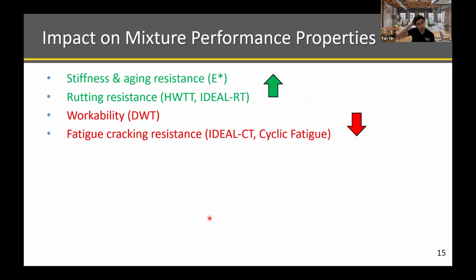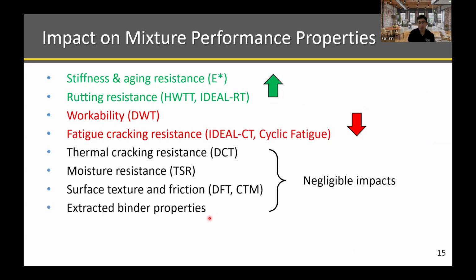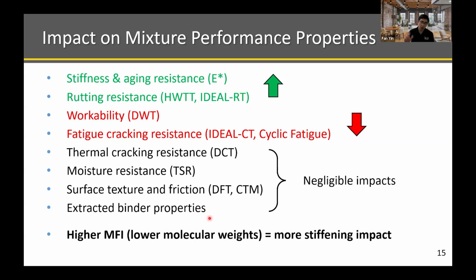In terms of impact on mixture performance, we saw pretty much the same trend as what we learned from the test track research. We saw the stiffening impact by looking at the stiffness or rutting resistance, which can be beneficial for those who are struggling with rutting. But we saw a detrimental side on the workability and the fatigue cracking resistance. And for the other properties we looked at in the very comprehensive lab testing, they really did not have much significant impact. One more thing I want to mention is that recycled plastics are very different. Very interestingly, we found that the recycled plastics with a higher melt flow index, which, relatively speaking, have lower molecular weight, are the ones that have more significant stiffening impact. So it goes back to what I said a couple of times: it's not just recycled plastic, the type and the property of the recycled plastic really matter.